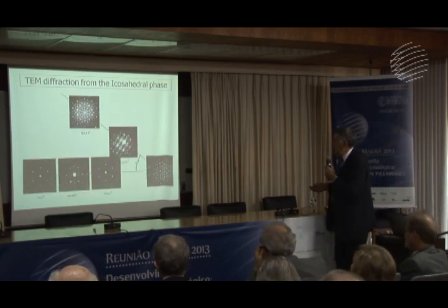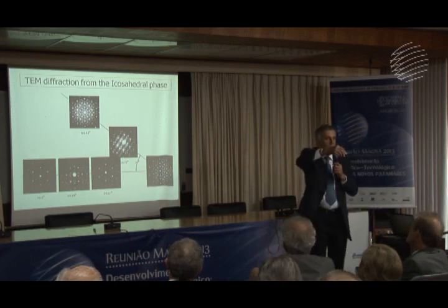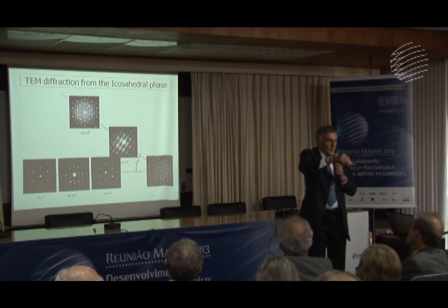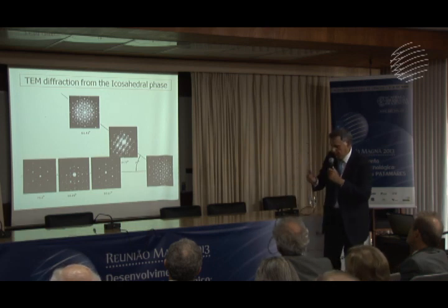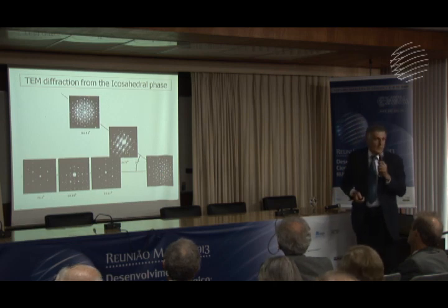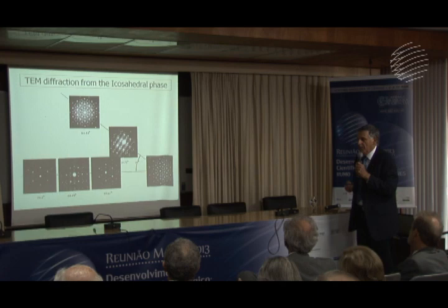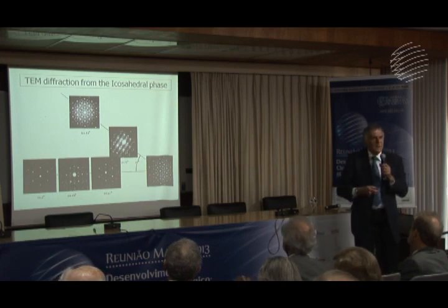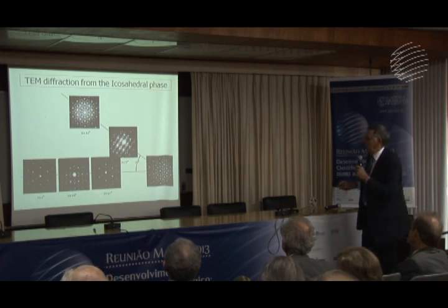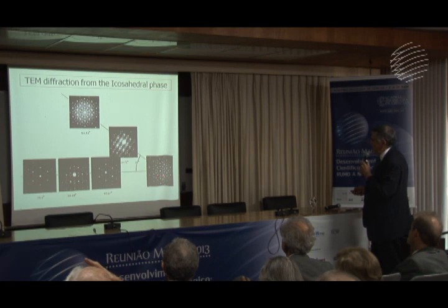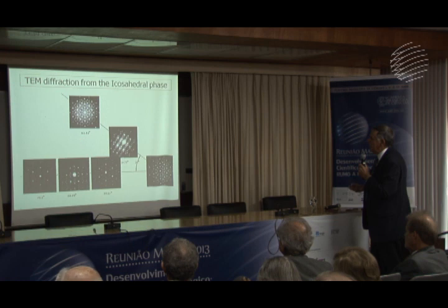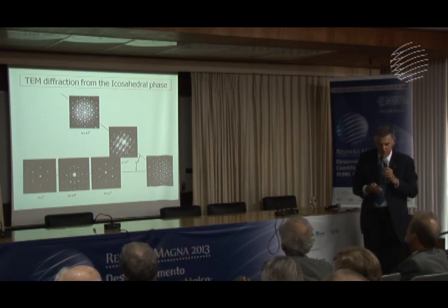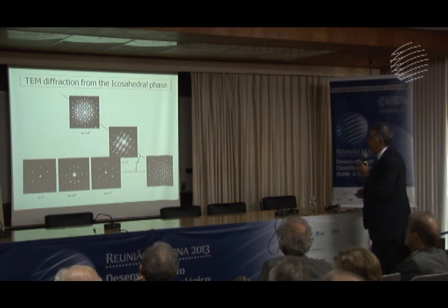But before doing that, these are other diffraction patterns. You see, you can take your crystal, and you can tilt it to different orientations, and you can rotate it to different orientations and take diffraction pattern in each and every relevant orientation. So this is what I did. And so this is the tenfold. Turns out, by the way, that it is fivefold, but you cannot tell it by looking at the diffraction pattern. Later on, I took Kikuchi patterns, which is something else, and that told me, hey, that's really fivefold. But that's not important now. So here is five, twofold, fivefold again, and in another direction, 5, 3, 2, and 3. And this is the set of diffraction patterns that defines an icosahedral symmetry. And I will tell you about the icosahedron in a couple of minutes. So this is the set of diffraction patterns.